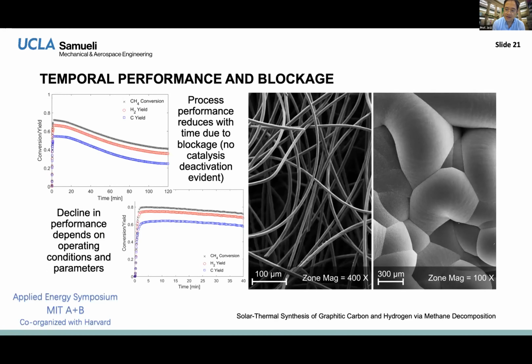And then you mentioned this turbostratic disorder in the graphitic carbon. I think the battery people and the supercapacitor people have different demands on the amount of disorder in the graphite. I think for a lithium-ion battery anode, maybe they don't want so much turbostratic disorder. But for fast charging and discharging, and maybe for a sodium-ion battery, they could want more of this rotational disorder. So has anyone evaluated this carbon material in that kind of energy storage setting?